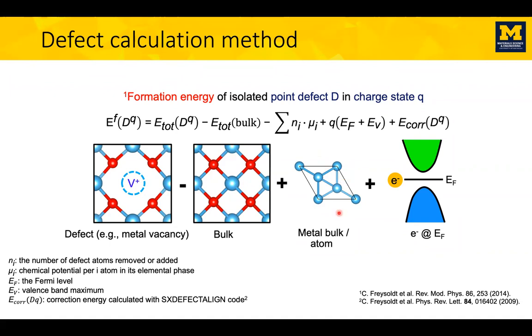The reference state can be either the bulk metal phase, if you're talking about the metal atom. It can be the oxygen gas phase, if you talk about the oxygen, or any other phase in the phase diagram, honestly. The defects can also be charged. They may have an electron trapped in them, or they may be positively charged, having lost an electron. So we need to say also what happened to any electrons we added or removed. And those are being exchanged with the Fermi energy, right? Electrons from the Fermi level may move to your defect or vice versa. The defect may lose electrons to the Fermi level and become positively charged. That's why you see these terms in the equation. And so charged defects depend on the Fermi level.